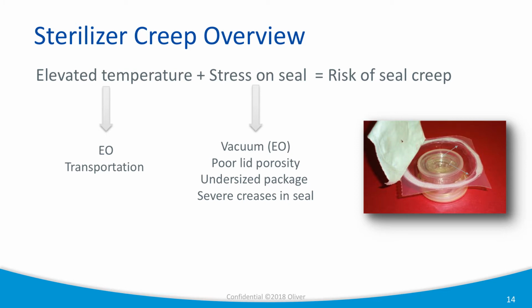So creep resistance meaning, think about EO, it's warm temperatures, it's humid conditions, it's pressure, inflow and outflow of gas, so you want your adhesive to be strong at those elevated temperatures. So just a quick pictorial of what I'm talking about. Again, you've got elevated temperature, stress on the seal from the vacuum, lid porosity, and that again is a nice picture of seal creep produced during EO sterilization, those little scalloped areas. That's where the adhesive is starting to give way and you're getting partial open seals, and in some cases, in this particular situation, the seal opened all the way.